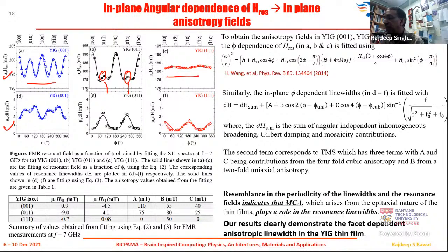And these can be fitted with different equations, which you can find from the literature, where you have this anisotropic field for the 4-fold symmetry or uniaxial symmetries. By fitting these equations, you can calculate the value of H4 and H2, which are listed in these tables. If you look at these tables, you will find that the H4 value for the 001 is the strongest, showing that it has a strong cubic anisotropy, whereas for the 011 it is predominantly uniaxial, H2, because that value is the highest, and it is very low for the last one, almost like no anisotropy over here.